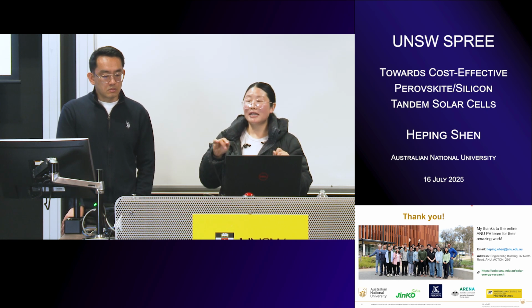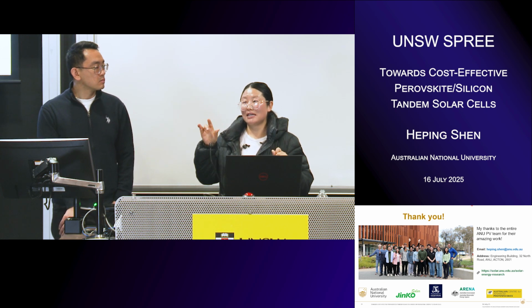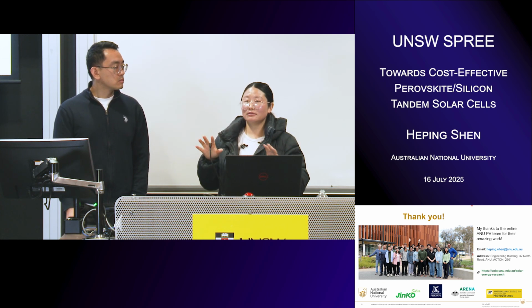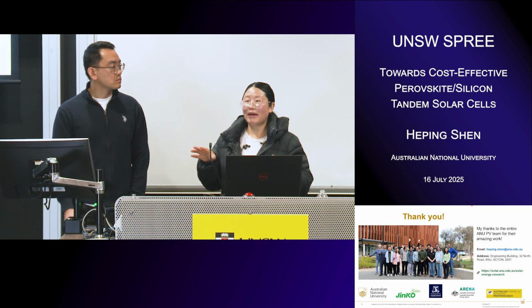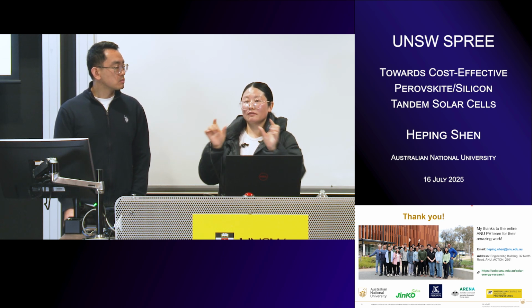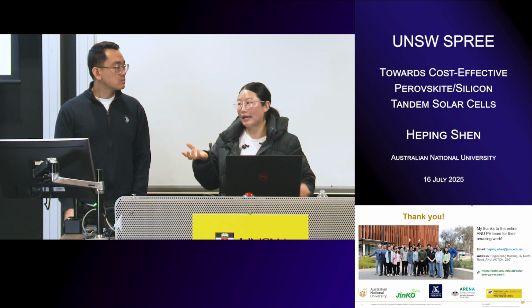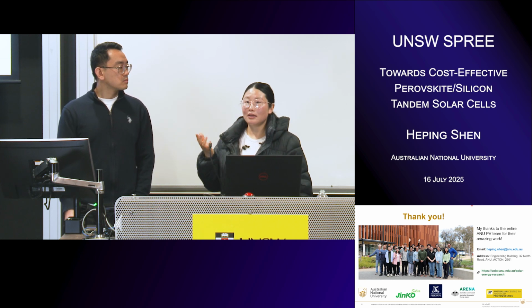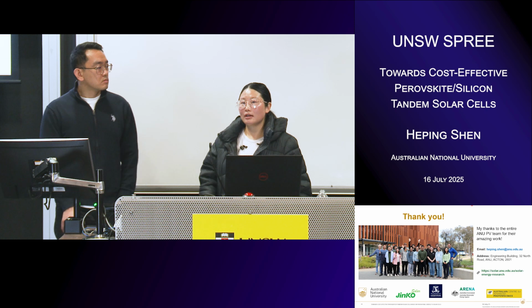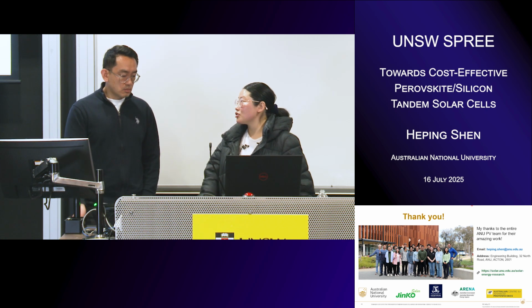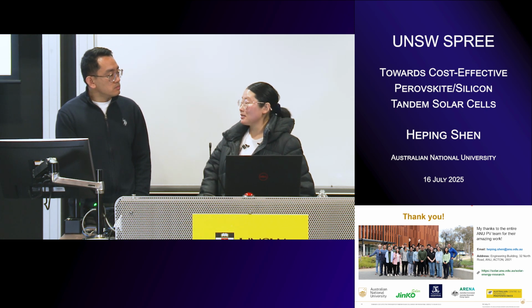But in the structure I shared just now, we have the ALD titanium oxide. Titanium oxide itself is very isolating and it's an ALD-deposited layer, so it's very dense. So that at least avoids the risk of being shunted at the large scale. So we think that's another advantage. That's also what we are assessing in the large area.